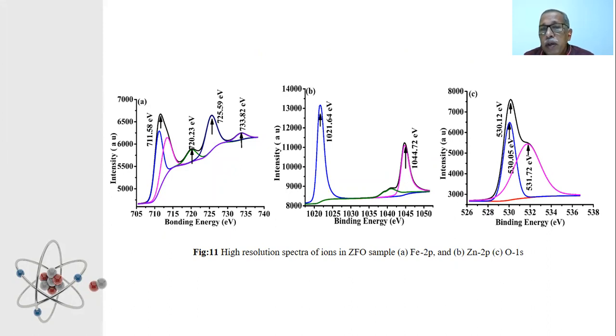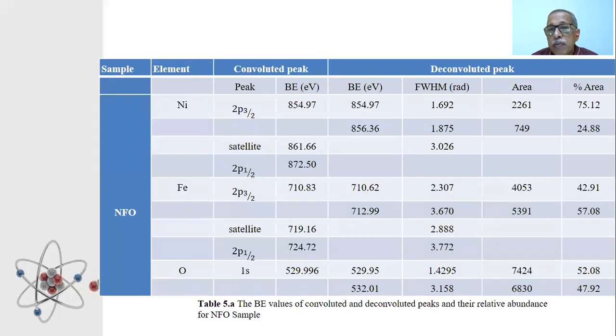The oxygen binding energy profile shows deviation from perfect Gaussian nature and it is deconvoluted to obtain the components at 530 and 531.72 electron volts respectively. The lower binding energy peak corresponds to lattice oxygen and higher peak corresponds to adsorbed oxygen. The peak area of each peak is determined. It is observed that adsorbed oxygen peak area is larger than lattice oxygen peak, which indicates that there exists oxygen vacancies in the material. Higher the oxygen deficiency, more will be its electrical conductivity and more will be the probability for gas sensing response of the material.